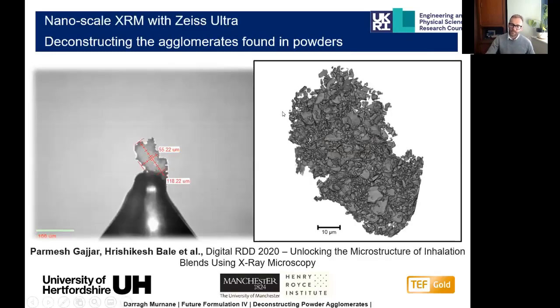So this shows the imaging that we've done with nano-CT and published recently at the RDD conference in the States with our colleagues from Zeiss. We can start to see the particle distribution within a single agglomerate of micronized particles. And you can see the scale here. Some of these individual particles are on the scale of about 200 to 300 nanometers. And we're able to now start to see the connectivity, the particle size distribution within those agglomerates, and start to build up an image of what the forces holding that agglomerate together are.